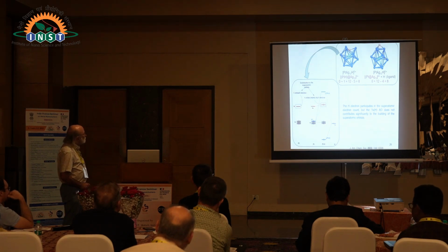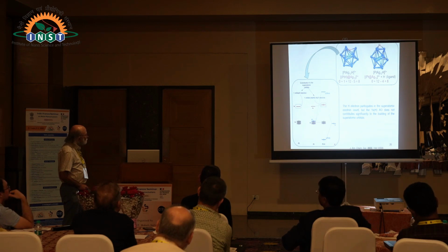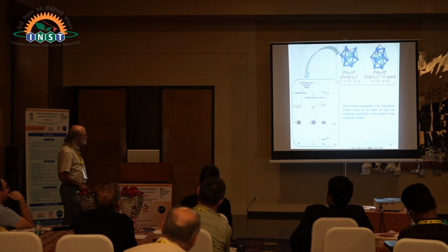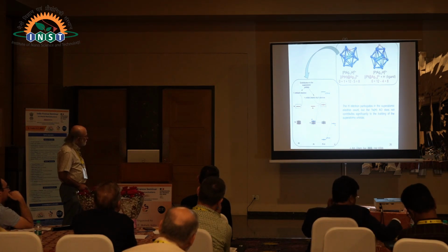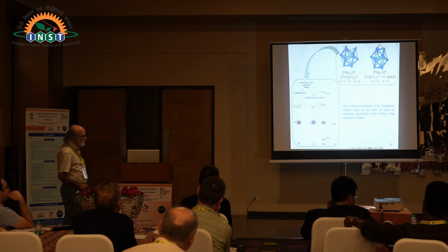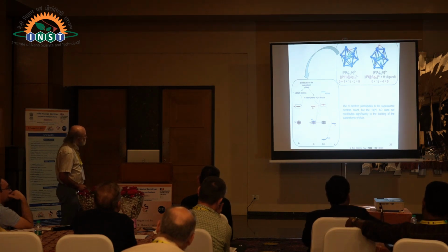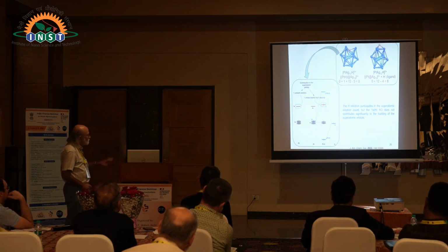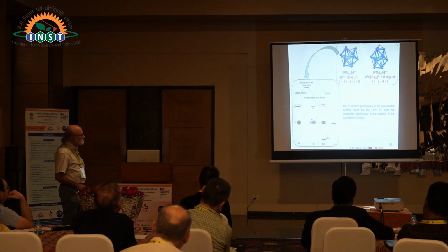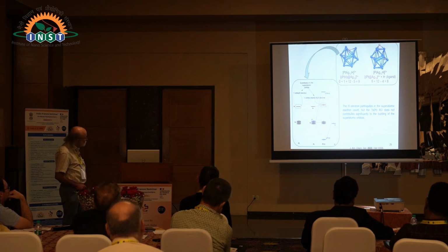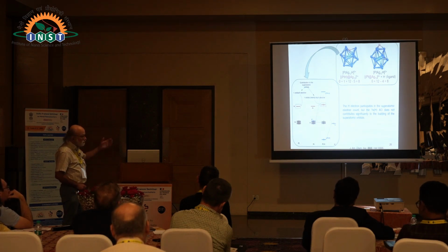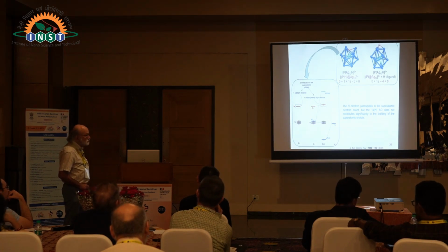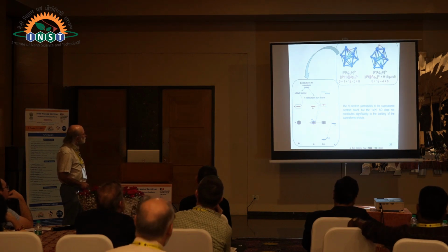If we add the hydrogen atom here, it will bind mainly to platinum, and the 1s orbital will interact with the dz2 orbital of platinum, making a low-lying sigma bonding orbital and a high-lying sigma star Pt-H orbital. The 6s orbital of platinum is not that much involved in the interaction. We can consider roughly that it remains the same. So it is still ready for interacting with the other s orbitals of the silver atoms to make superatomic orbitals.